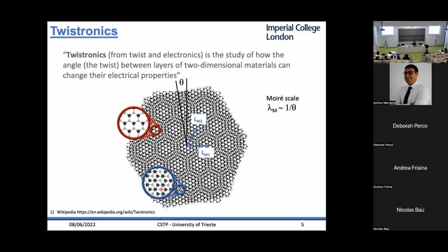In general, when you stack two 2D materials and apply a twist, this Moiré pattern has a periodicity which is much larger than the periodicity of the 2D crystal. In particular, the periodicity of the Moiré pattern goes as 1 over theta, where theta is the twist angle. So small theta means large Moiré cells. The other thing is that not for all theta can you have a so-called commensurate cell. Most of the time, this would be a quasi-crystal in a sense, because this region here would be slightly different from this region here. But at some specific angles, you have a commensurate structure, and this structure is fully periodic.